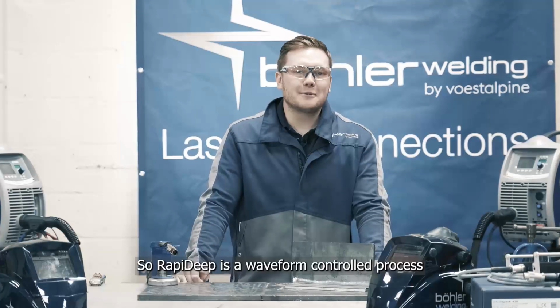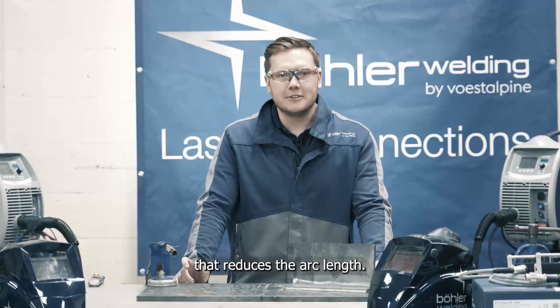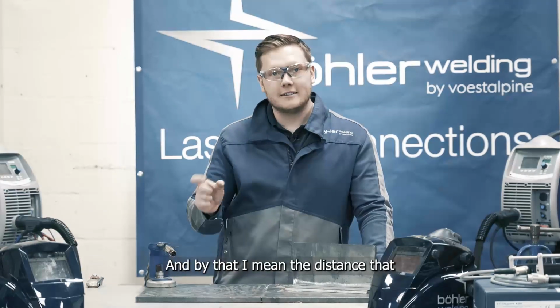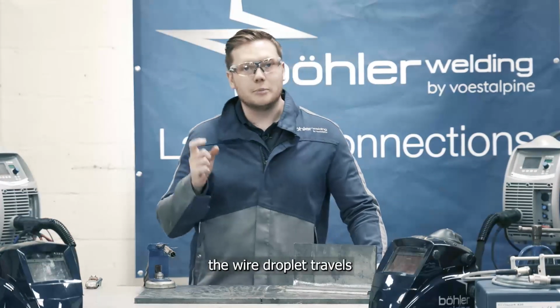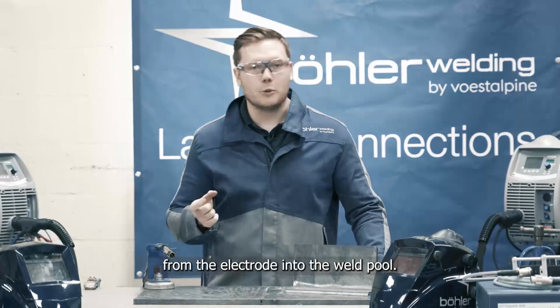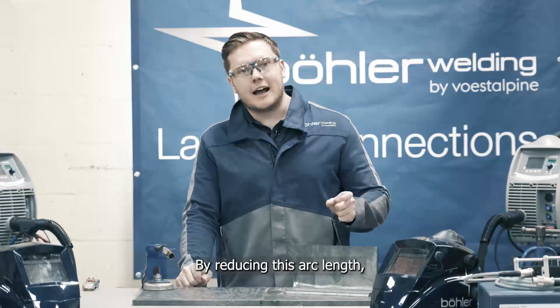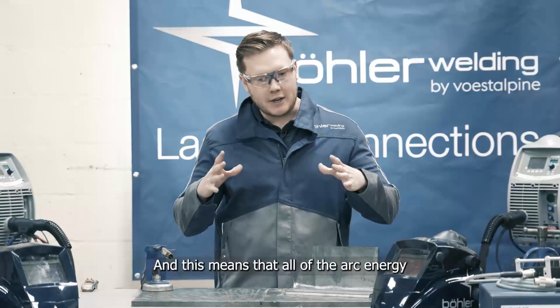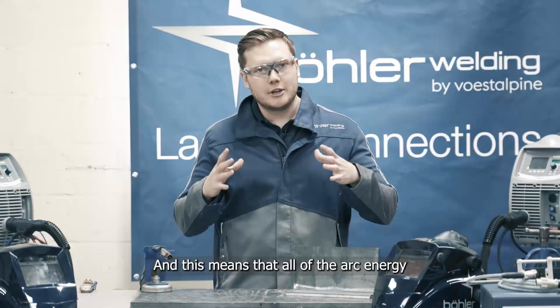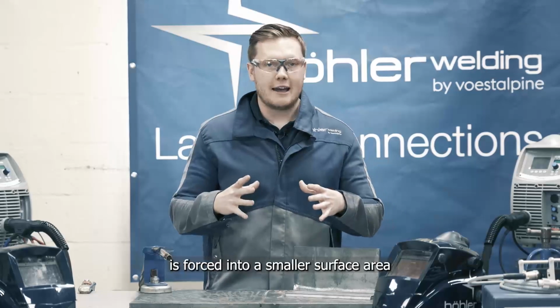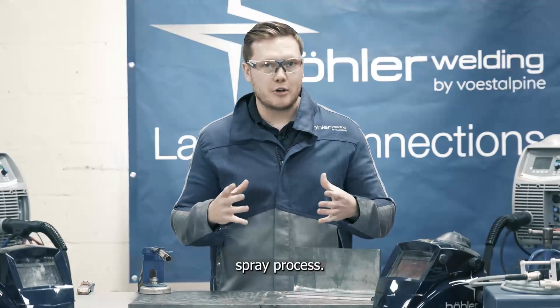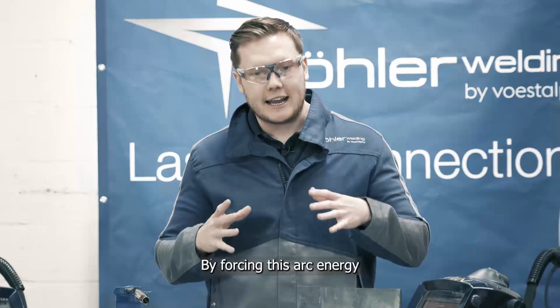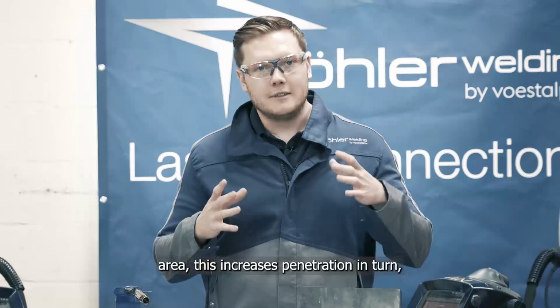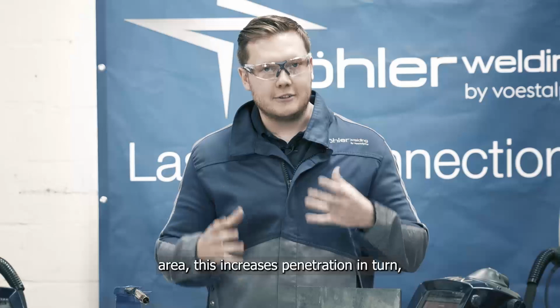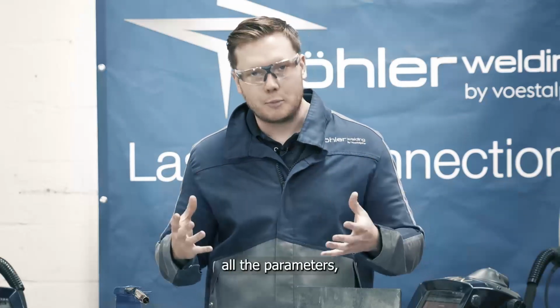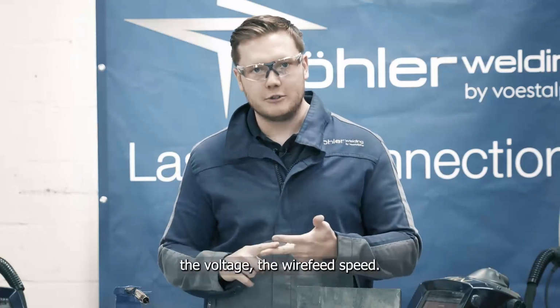So RapiDeep is a waveform controlled process that reduces the arc length, and by that I mean the distance that the wire droplet travels from the electrode into the weld pool. By reducing this arc length, we reduce the arc cone, and this means that all of the arc energy is forced into a smaller surface area than it would be in a standard short spray process. By forcing this arc energy into a smaller surface area, this increases penetration, in turn allowing us to increase other parameters, the voltage, the wire feed speed.